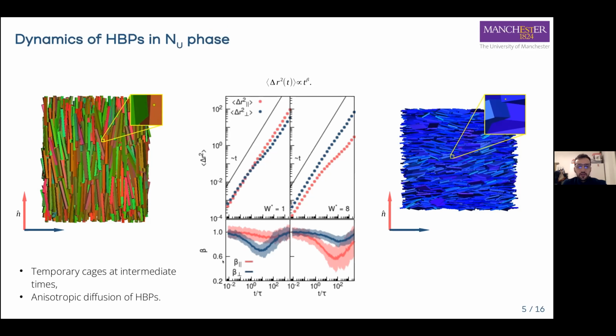And we observed the formation of temporary caging effects for the particles in specific directions, depending on the main orientation of the nematic phase, at intermediate times. And also, as I said, the anisotropic diffusion of hardball-like particles that preferentially move in the direction parallel to the nematic director for prolate nematic phases, and in the direction perpendicular to the nematic director in oblate nematic phases.